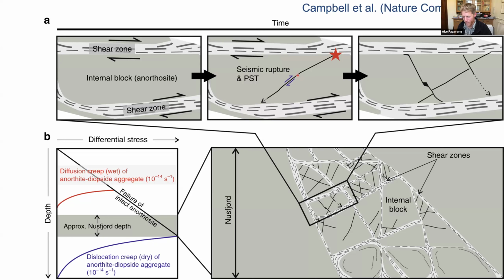It has the properties to then deform by seismic sliding, but these pseudotachylites seem to then stop at the shear zones. It's hard to tell exactly because they're then subsequently deformed, but we never see these pseudotachylites cross-cut the shear zones. We've never found one that we can find again on the other side. So they seem to be related to or constrained to the block that deforms. Remember also that we're at 700, 800 degrees already, so you don't need a lot of slip before you potentially hit the melting point. Yeah, thank you.